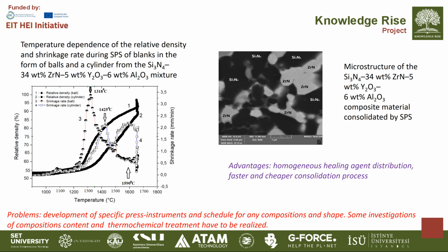The results reveal efficient consolidation, homogeneous microstructure, and improved distribution of the healing agent. This demonstrated the potential of SPS for development of highly dense self-healing ceramics. We densify it at relatively low temperatures, up to 1650 centigrade, and characterize the microstructure, and here you can see that the healing agent, zirconium nitride, is homogeneously distributed in the volume of the silicon nitride composite.